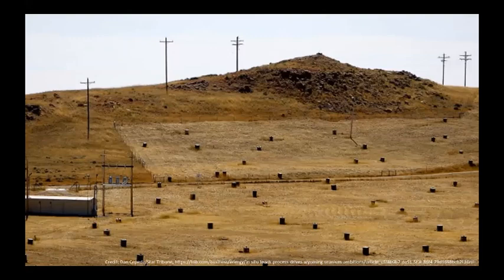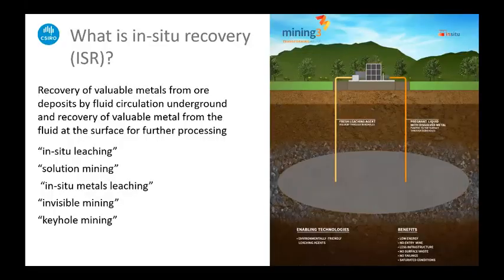And I'll show you a schematic on the next slide that explains this in a bit more detail. So essentially, in-situ recovery involves the injection of fresh leaching agent, or lixiviant, or solution underground into the region of interest where the value is in the deposit, the dissolving of the value metal and also gangue minerals, and then the pumping of this fluid back to the surface for further processing. And the further processing at the surface is often by conventional means, so for example, solvent extraction and electrowinning.